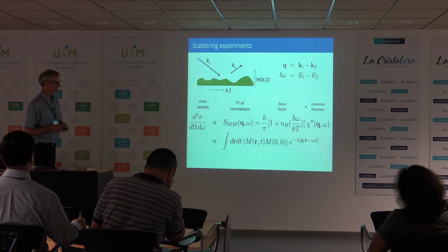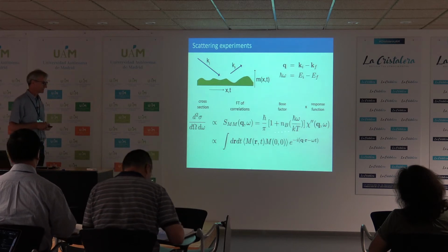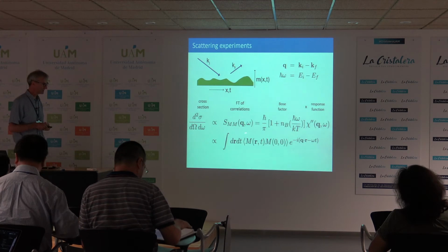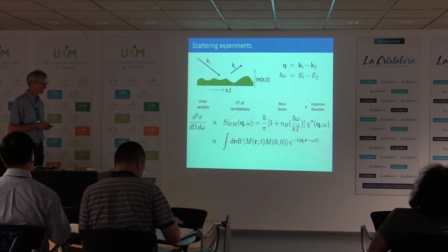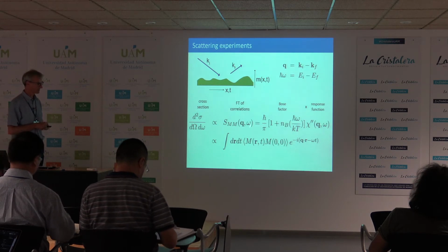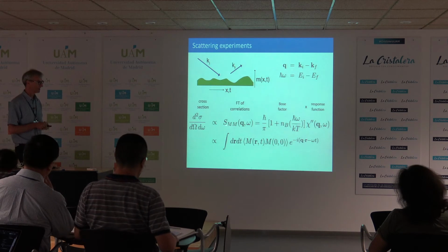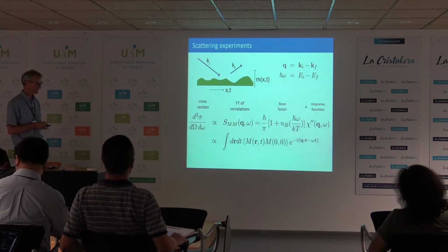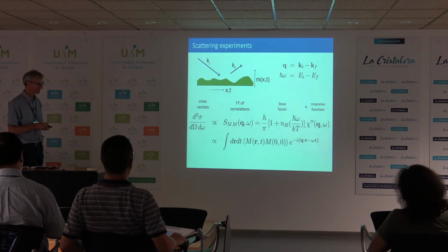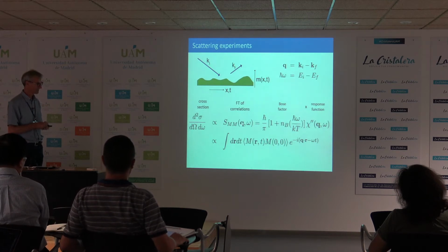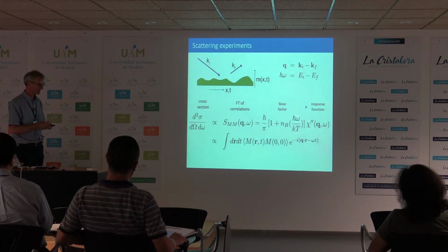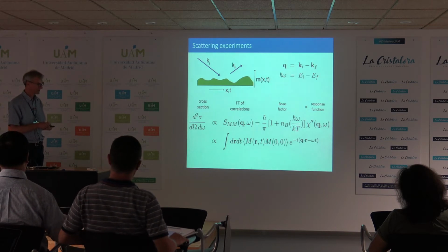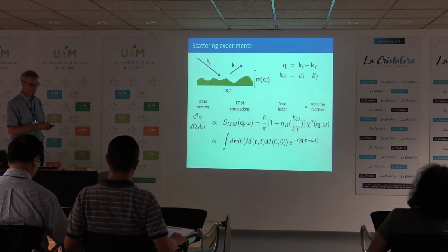But finally, just for completeness, another useful tool in scattering experiments is the fluctuation dissipation theorem, which allows us to relate the susceptibility with a Bose factor to actual fluctuations in moments. So this is like the power spectrum, we call it, of the moment fluctuations in our solid, can be related to this quantity. And this quantity is actually what we measure. Another way of seeing neutron scattering is to say this: we measure this quantity, we can remove what we call the Bose factor, the one that's used for neutrons here, and obtain the response susceptibility.